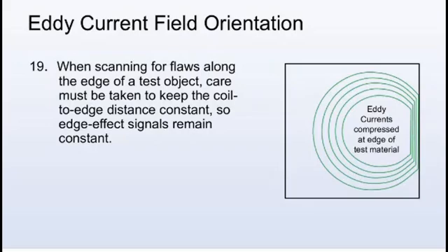When scanning for flaws along the edge of a test object, care must be taken to keep the coil to edge distance constant, so edge effect signals remain constant.